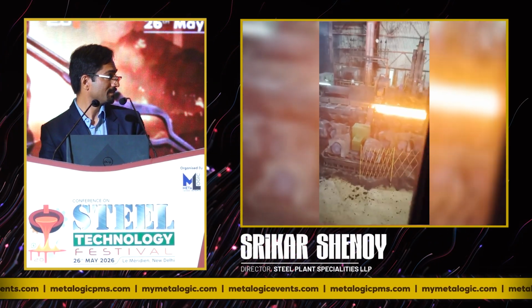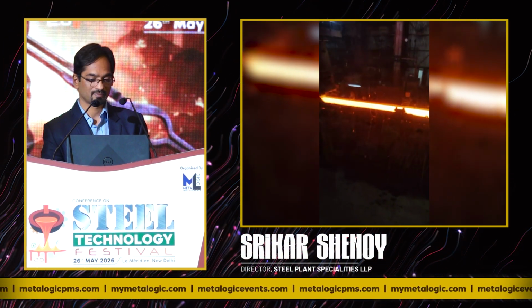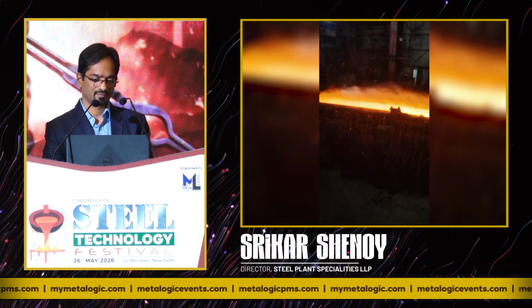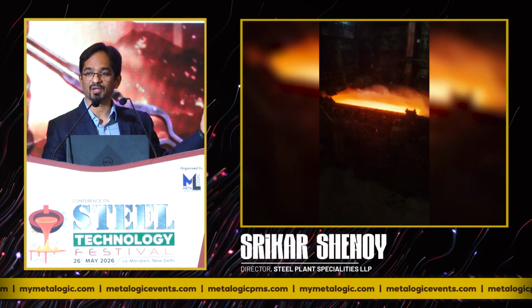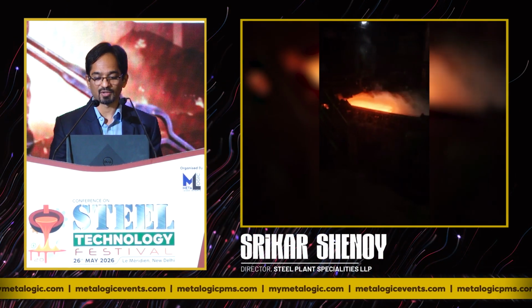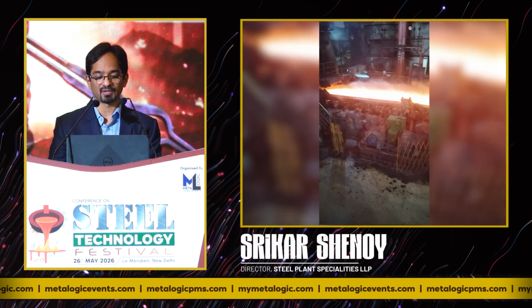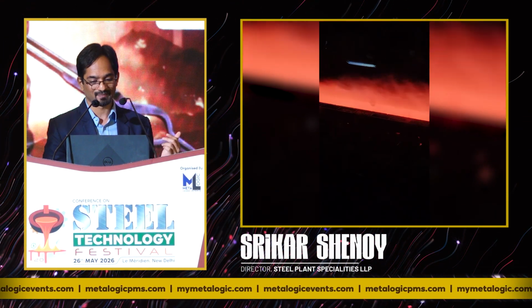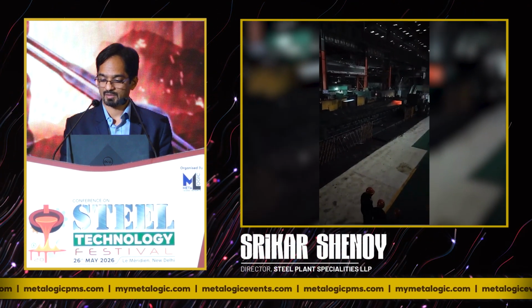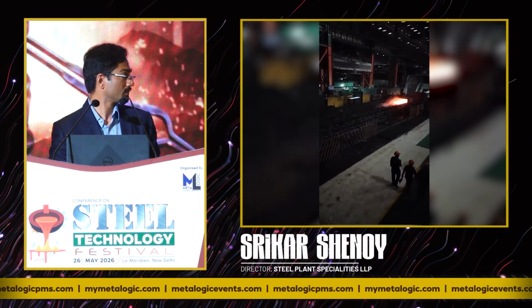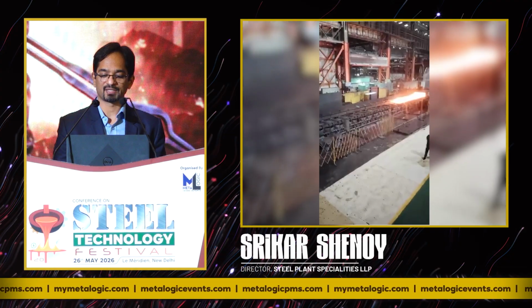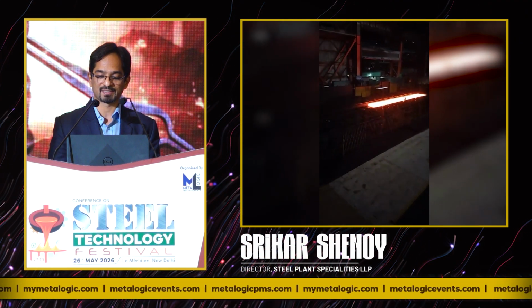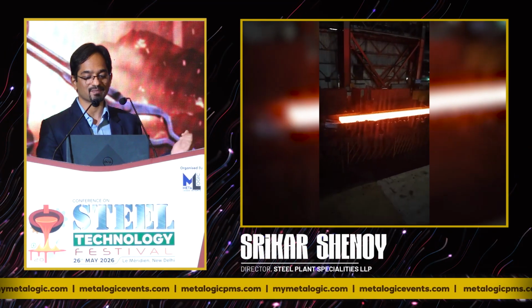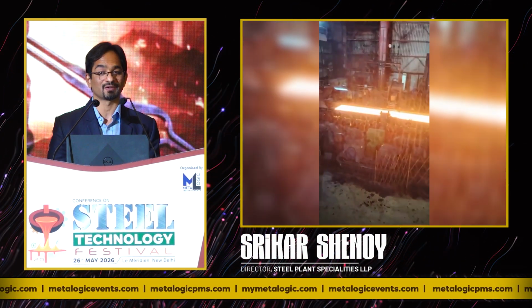Look at this now. Imagine making a rolled product using this. You would definitely have irregular surface finish in many cases. In this particular case, the end product is a 2 mm thin sheet, and this scale was actually causing through and through holes. And in the same organization where the slabs are coated with the customized metallurgical coating, the descaler is much more effective, and what you'll see is a good surface finish.